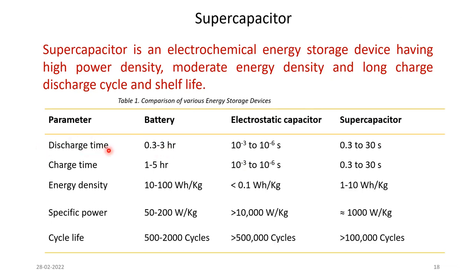Now let's talk about discharging time. A battery has a discharging time of usually 0.3 to 3 hours, whereas the electrostatic capacitor is very fast, charging and discharging in the 1 millisecond to microsecond range. In supercapacitors, the charging and discharging times are about 0.3 to 30 seconds. The energy density of a battery is 10 to 100 watt hour per kg, for electrostatic it is 0.1, and for supercapacitor 1 to 10 watt hour per kg, meaning the energy density of a battery is much higher than a supercapacitor, but the power density of supercapacitors is higher than a battery.